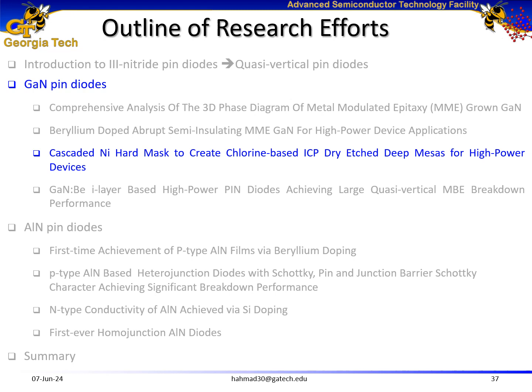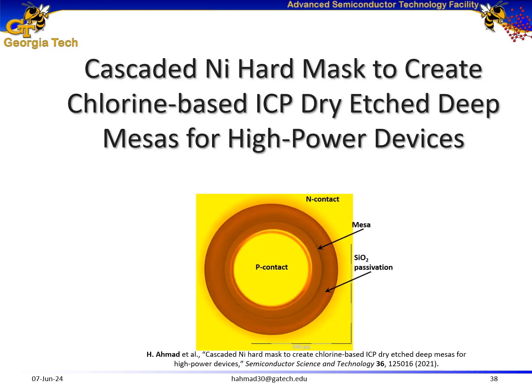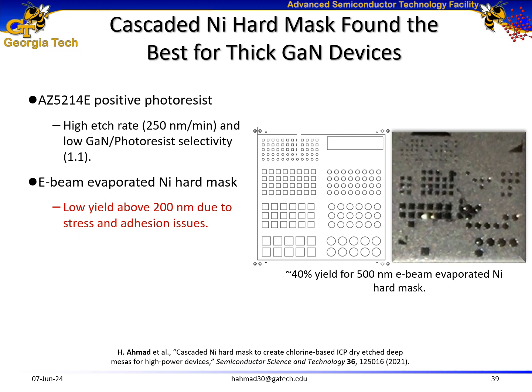So next, I wanted to focus on gallium nitride pin devices, but the plan was to grow thicker gallium nitride pin diodes in the range of 3 microns to 13 microns, and that required an optimized fabrication process as well. So I performed a study on cascaded nickel hard mask to create chlorine-based ICP dry-etched deep mesas for high-power devices. In this regard, I performed a study on 5 different kinds of masks.